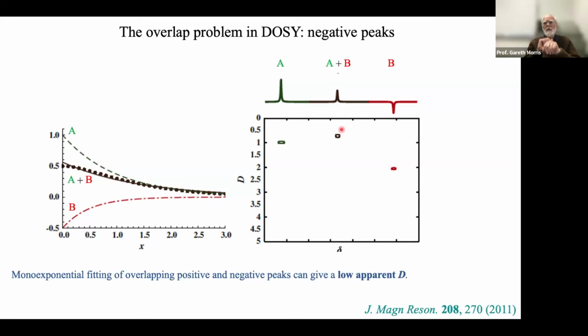And if we use too long a delay for our encoding, longer than a millisecond or two, then we can get some J modulation. And we see a little bit of dispersion mode mixed in with the absorption mode. Oh, and I should say that the same type of changes in apparent diffusion coefficient come about from baseline errors.